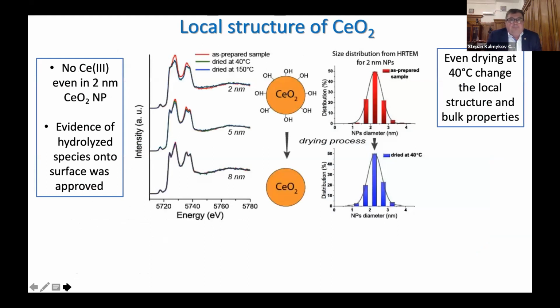The interesting thing is that we used different drying processes, and we tried to heat the samples, and the spectrum changed upon these changes of the sample. So what we think is going on is that upon drying and upon heating of the sample, especially for 2 nanometer size particles, where we have a lot of atoms on the surface, when the surface atoms start to be very important, we have a difference between, for example, as-prepared very fresh samples compared with the dried samples, and say nothing about the sample dried at 150 centigrade. So we can explain it by the change in the surface and the effect of the surface hydroxyl groups, which is different for as-prepared fresh samples and those dried at different temperatures.